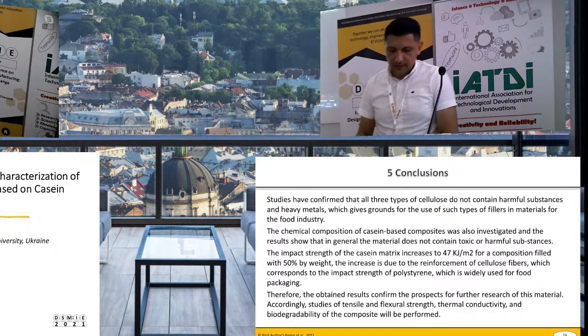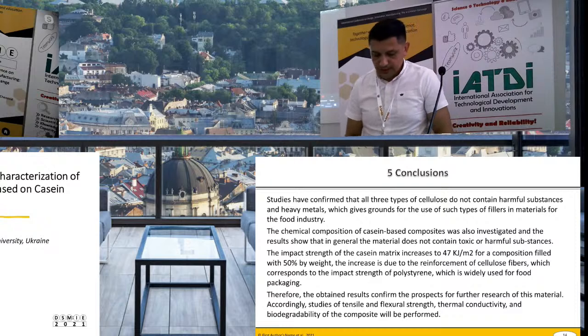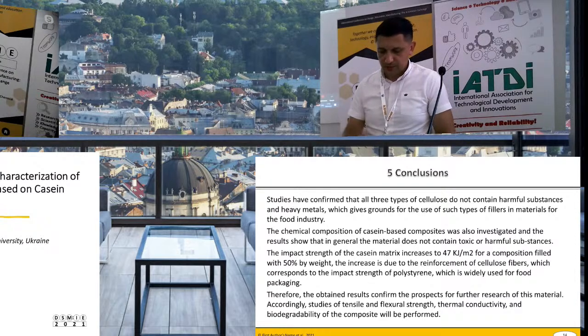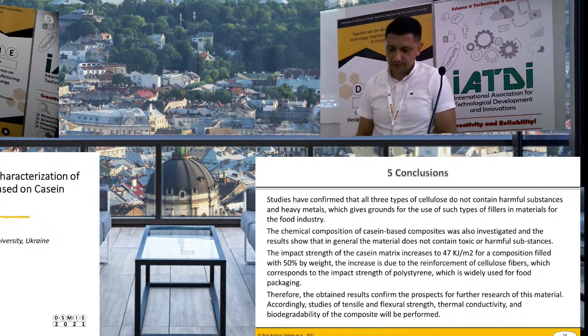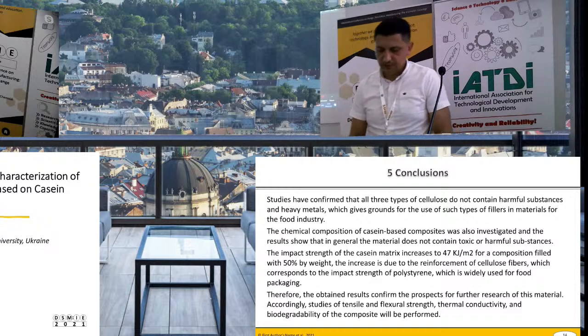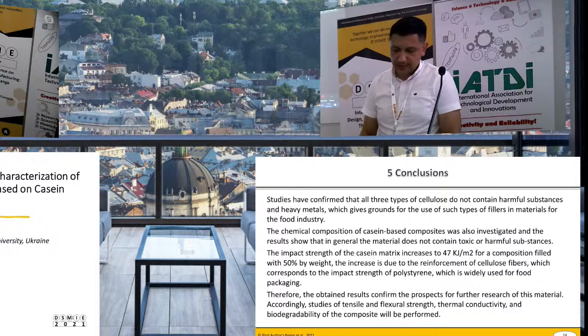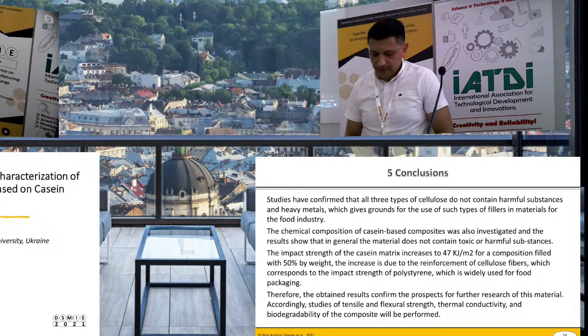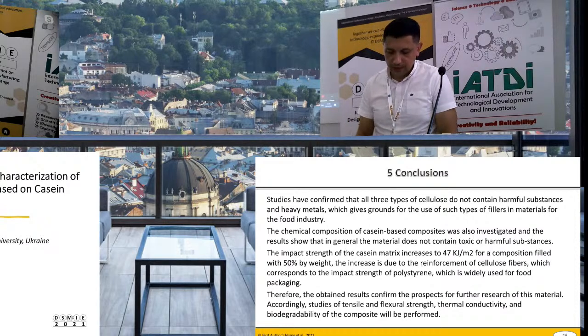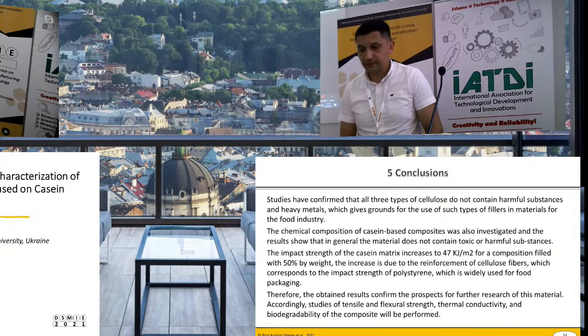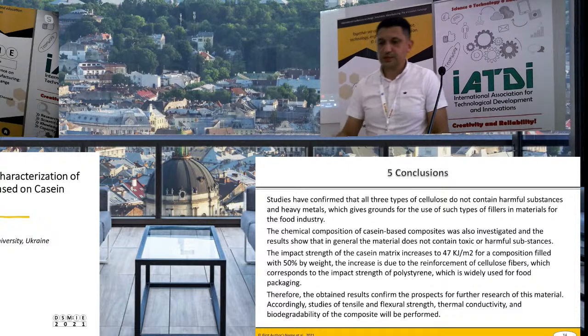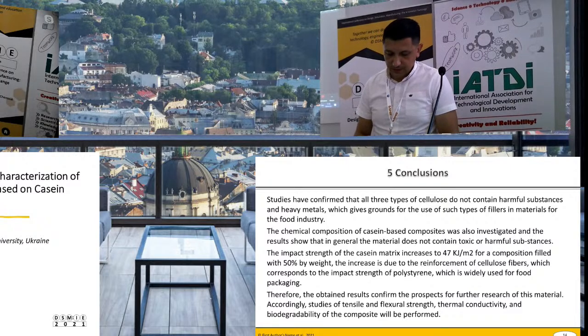Conclusions. The chemical composition of the casein-based composite was also investigated, and results show that in general the material does not contain toxic elements. The impact strength of the casein matrix increased to 47 kilojoules per square meter for a composition filled with 50% by weight. The increase is due to reinforcement by cellulose fiber and corresponds to the impact strength of polystyrene, very well known and widely used to produce packaging. Therefore, the obtained result confirms the prospect for further research of this material.